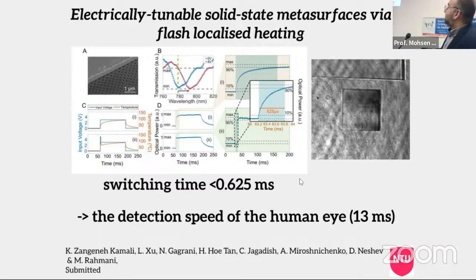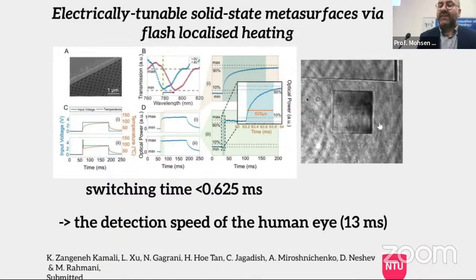So by some electronics tricks, we managed to bring this switching time down to 625 microseconds, which is 20 times faster than what our eyes can see. So if I turn on this video, you see that we are changing the frequency of this. We are applying voltage on and off, on and off. It is the same structure, the same thing, a really thin metal surface, around 30, 40 nanometers. And you see that we can turn it on and off and use it as an optical switch. And at some point, you cannot see that. You don't see that it's turning on and off. It goes beyond the response of our eyes.